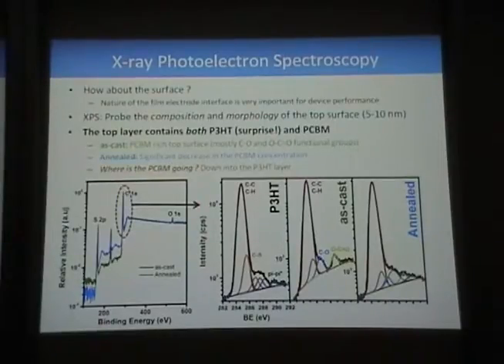Now, if you look closely at the carbon 1s peak, what you see for the as-cast sample is contributions from the carbon-oxygen functional group from the PCBM. They're in the ratio of 1 to 1, as you'd expect. And once you anneal, you see a significant decrease in the contribution from those functional groups, and at the same time, a rise in the contribution from the carbon-sulfur bond over here. So where is the PCBM going? Well, we think it's going down into the P3HT layer.